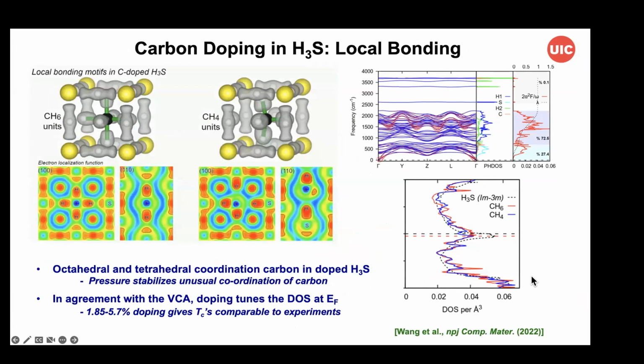This is work that was pioneered by, or led by, the Buffalo group in collaboration with us. We found that, in fact, pressure and chemical composition in this system can stabilize carbon in octahedral coordination by hydrogen, which is quite interesting. And there are parallels to the molecular ions that you can make and observe at ambient pressure. And we also looked at the shift in the density of states and the shape of the Van Hove singularity as a function of this doping in supercell calculations, so going beyond a virtual crystal approximation here.